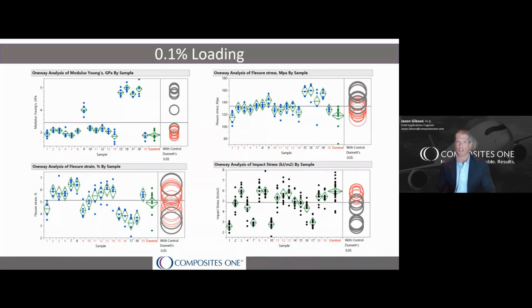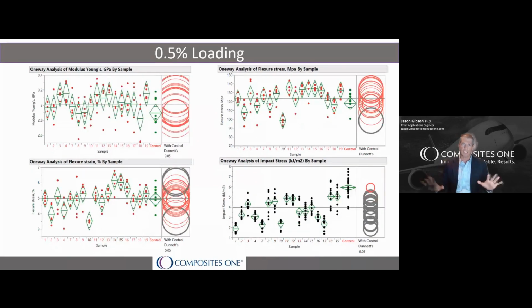So let's just take a moment and look at the same type of data for the 0.5% loading. So these are the same 4 graphs for our 0.5% loaded samples. Immediately in that top left graph of flexural modulus, you'll notice none of the samples tested showed any statistically meaningful change from the baseline, and all are in red. You'll notice that the spread of results is larger than those 0.1% loading that we showed you on the previous slide. There's simply too much variation in results to have any confidence in them being different from the baseline.